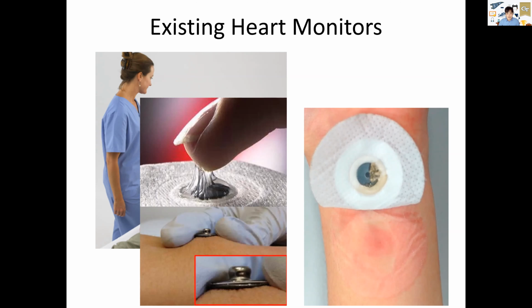So we are using conductive gels made of sodium chloride. That's good, but now the problem is that this conductive gel is evaporating over time. And also when it's combined with this aggressive adhesive, it can easily cause skin irritation, allergic reactions. And also because of evaporated gel, it can change the impedance over time, which can degrade the signal quality.